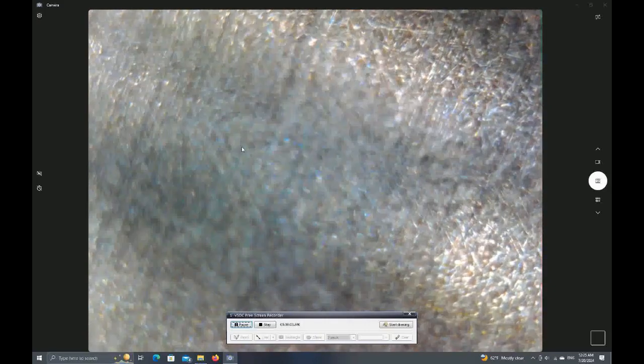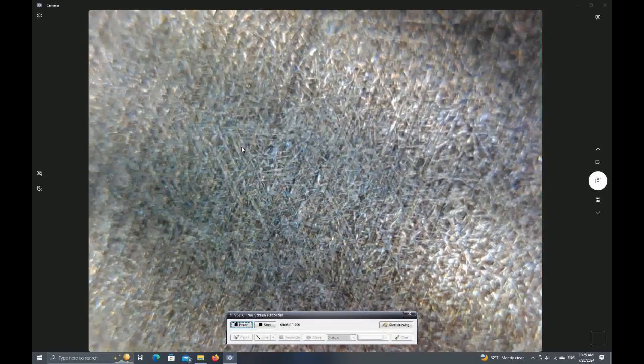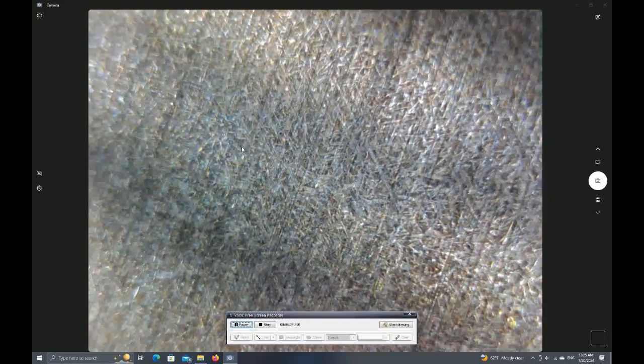The reason I didn't bother going all the way up to a micron finish is because I wanted to be practical about this. What I mean by practical is I'm presumably going to make knives out of this material, and you can absolutely bet your sweet bippy I will not be polishing those knives up to a micron finish, hand sanding, etc., and then etching. I'm going to be sanding them up to about a 320 grit finish, maybe 400, and what you see is what you get. So I wanted the etch that I studied with this little microscope to be reflective of what you would actually see in a finished knife made from this steel. But I'm really loving the coloration that I'm seeing here.